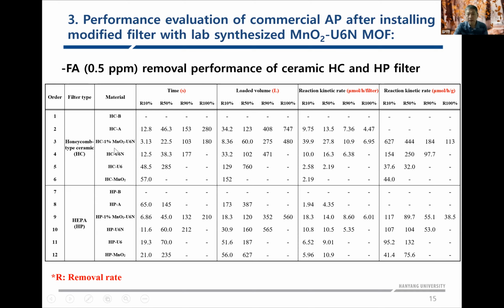Does it treat better than the honeycomb A with the light on or photocatalyst? Our result shows yes. Like honeycomb A, it took 280 seconds, but our room temperature thermal catalyst took even shorter, 180 seconds to remove 100%, and even far faster for 10%, 3 seconds versus 12.8 seconds.